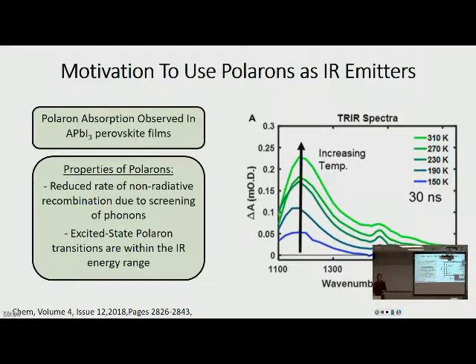Maybe there's an inversion point. At some point, maybe this would go down, but I guess the physical constraint is it has a pretty low melting point. So it can only go up to like 400K, maybe 450. But I think the reason that it increases with increasing temperature is it activates vibrational modes, like the methylammonium in the perovskite, and the activation of those creates the polaron. So that's why at lower temperatures it doesn't form. At higher temperatures, the vibrational modes have the energy to move with the charge, and then if you get too hot, it just melts. Right.